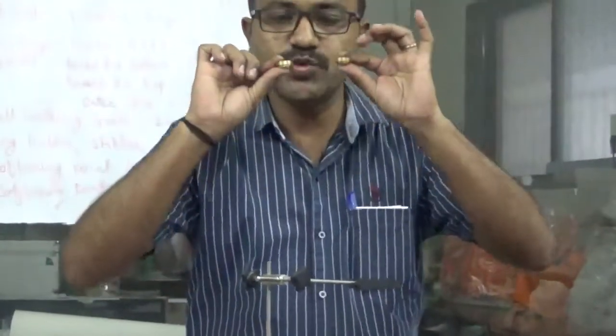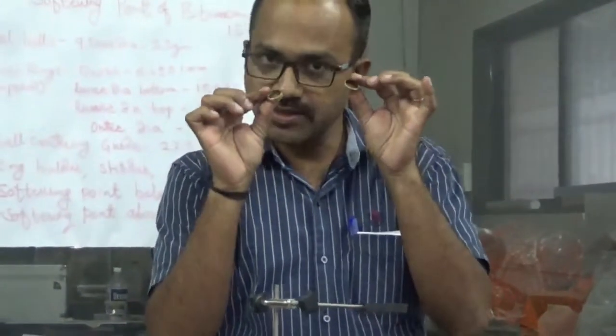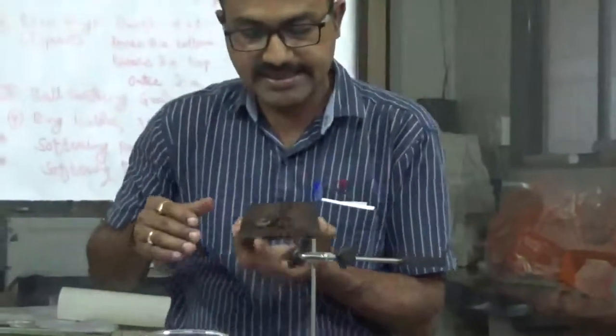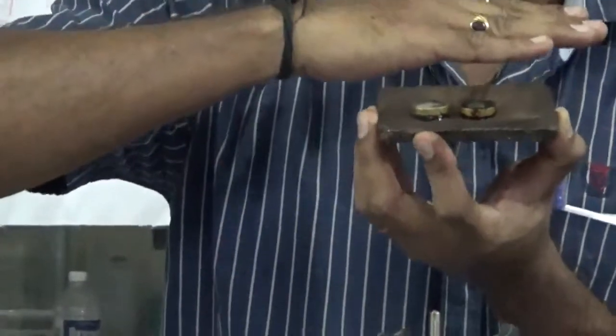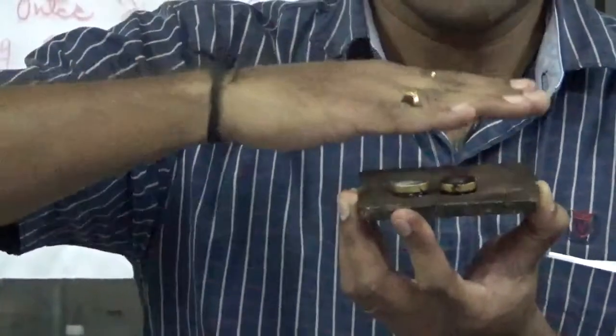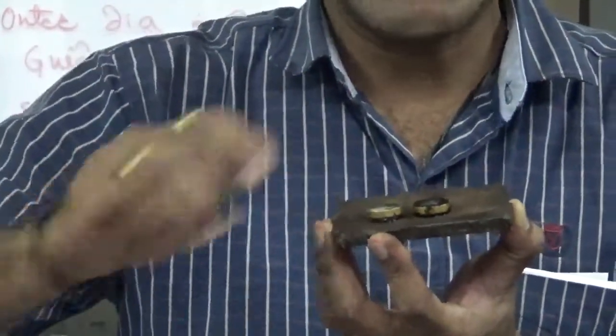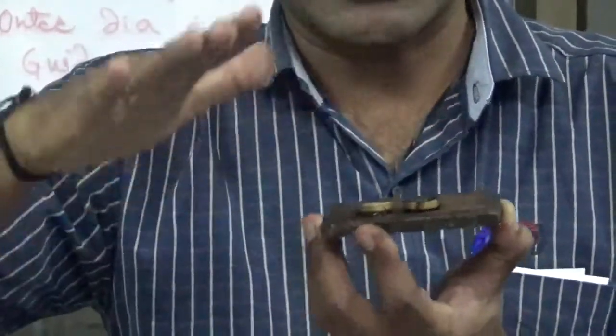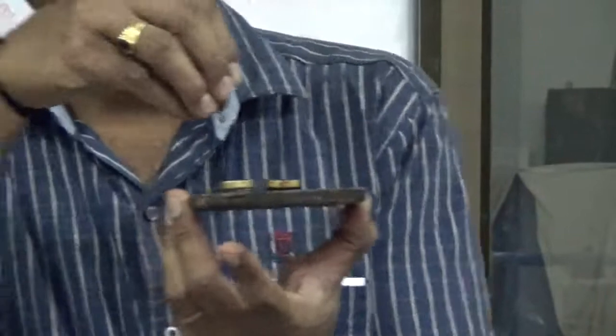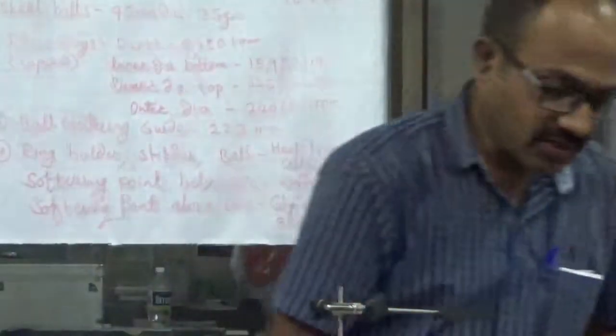After melting the bitumen, fill these two rings. After filling, you will see it like this. The excess material we are going to square off using a knife. So you can heat the knife and square off all the excess material from the rings. After filling the sample, let it cool to room temperature. After cooling,